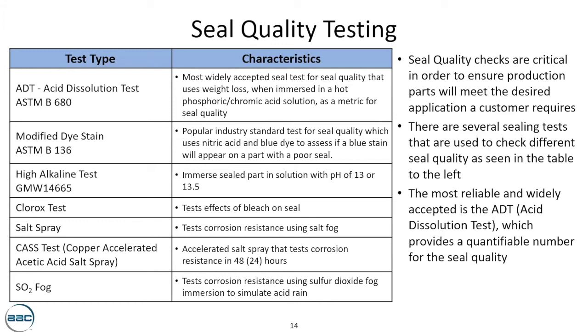The pH of this salt spray solution is generally between 6.5 and 7.5. Now, there are variations of this test where other chemicals are added to this salt solution. One such solution is acetic acid with copper, which gets us to our next test, known as the CASS test, or copper accelerated acetic acid salt spray test.